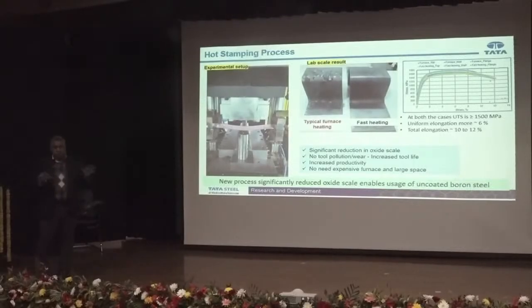Okay. This is very well common nowadays, people are using that day in, day out. But one of the problems with that is that right now it's furnace heating, and the furnace heating has certain limitations from the productivity point of view. Also you can't use uncoated boron steel because scale formation will happen, and that scale gets transferred onto the die, so die life becomes an issue. So people generally use aluminum silicon coated steel, and then you don't have that problem of corrosion.